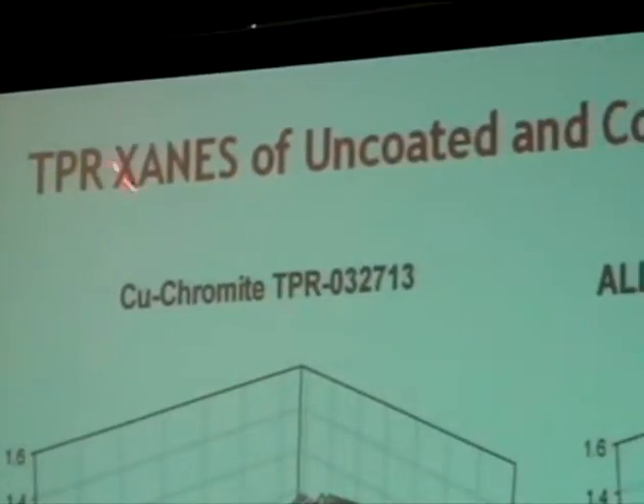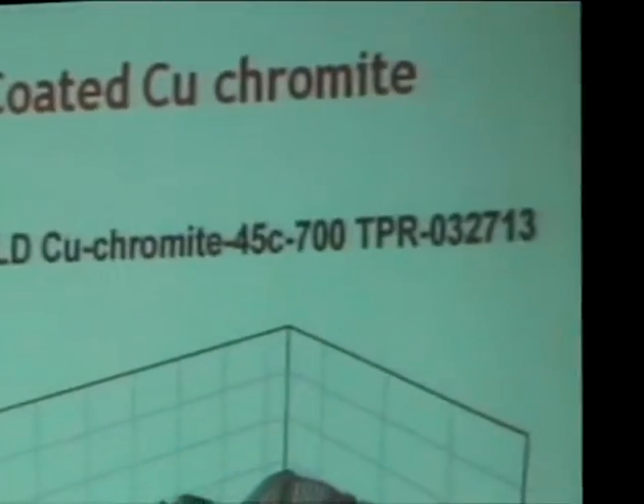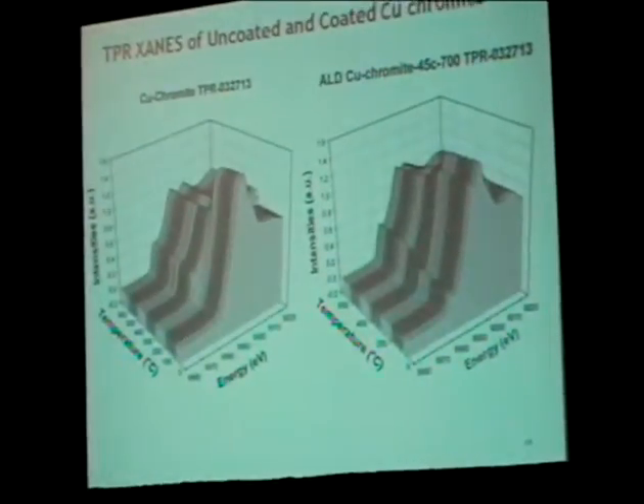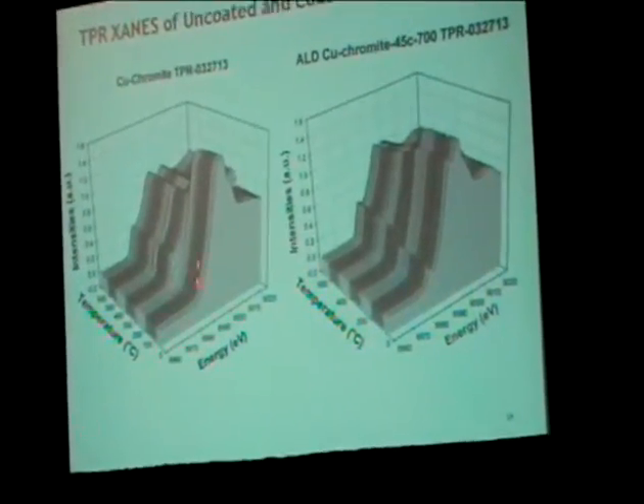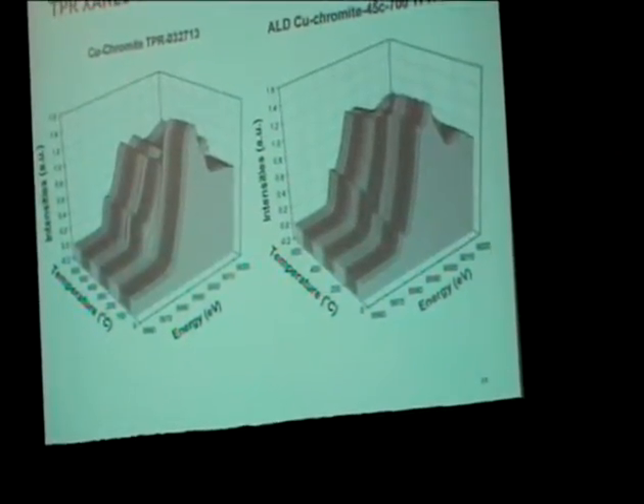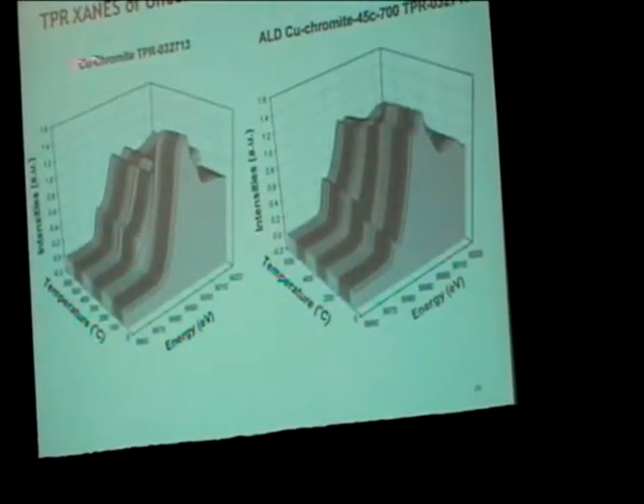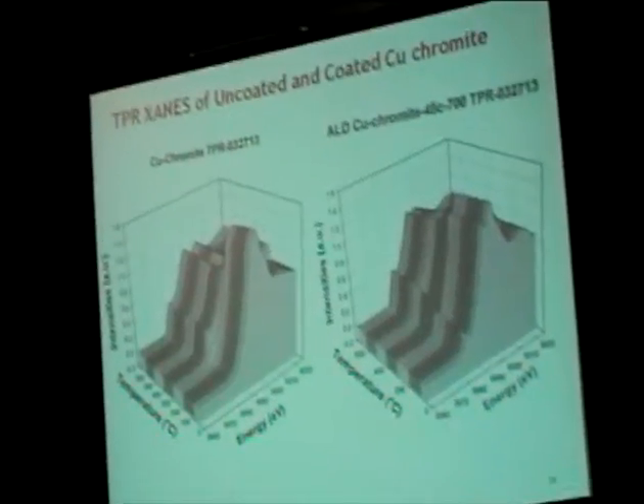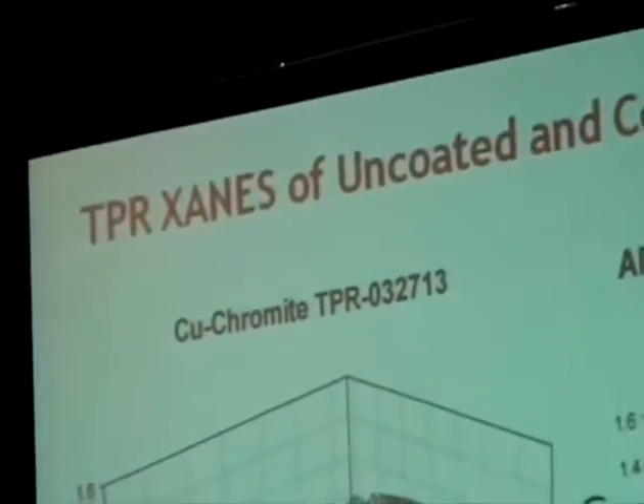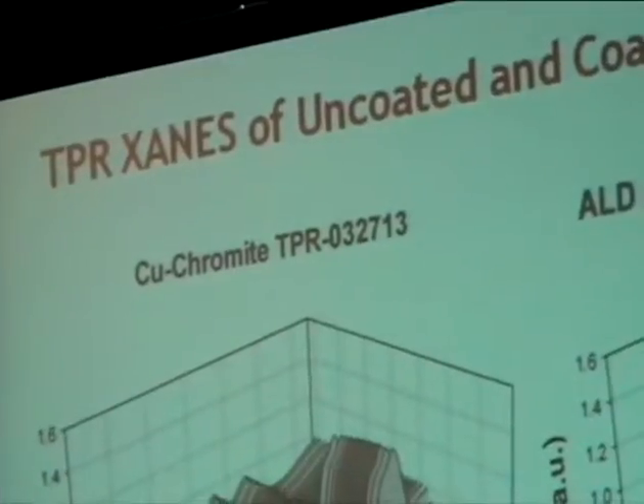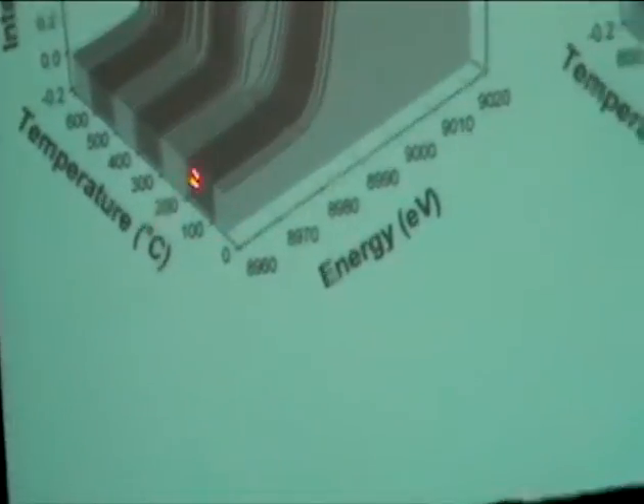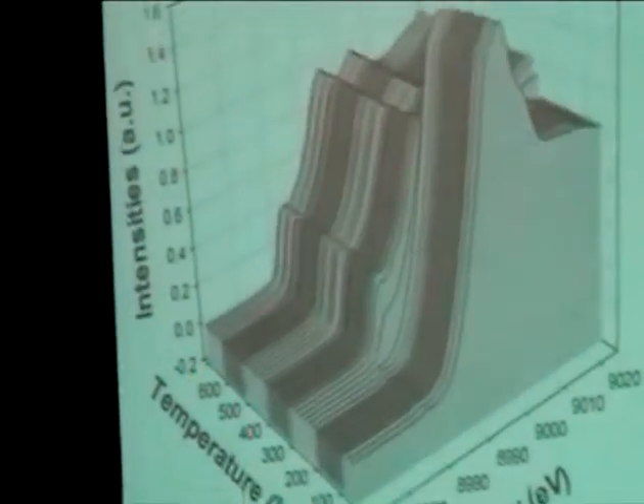Here's a stacked plot of the TPR XANES for either the uncoated material or the coated copper chromite material. On the left is the uncoated material, and as I said, this is new data. You can see the date which we collected that information. It was just last month. Here's the XANES data as a function of temperature, again in flowing hydrogen.